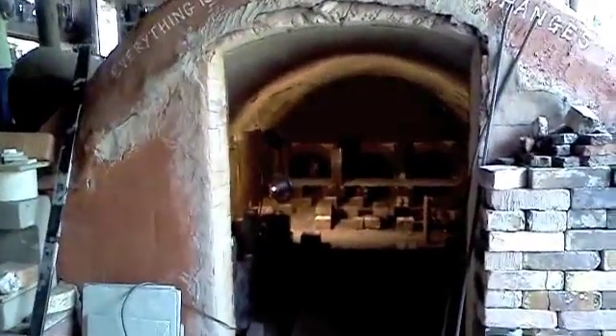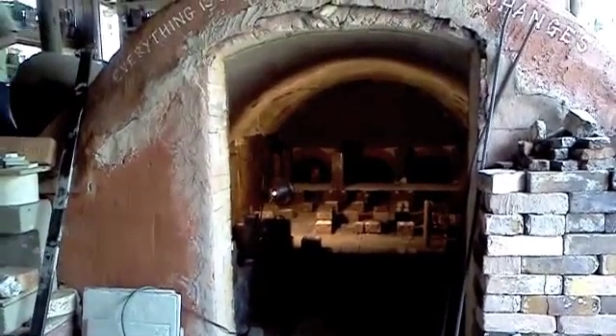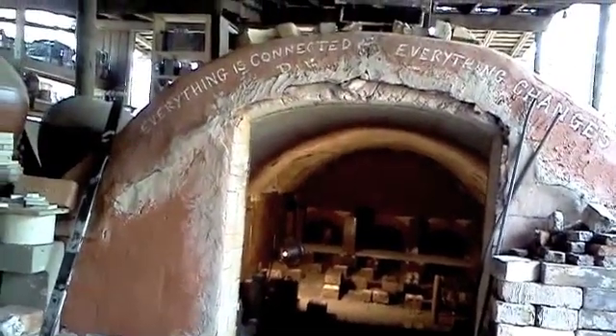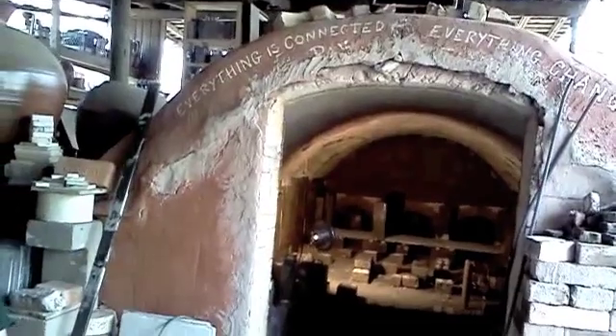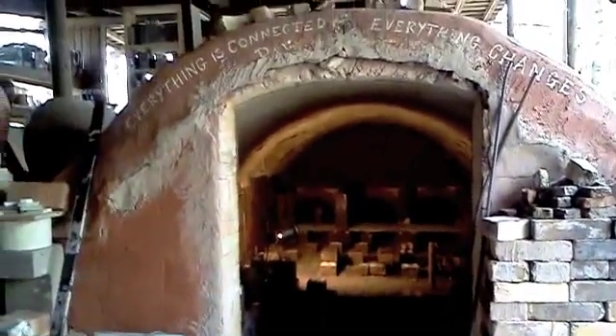And we start preheating on a Monday, and then by Thursday we're pushing the fire underneath the grate. And then by 6 or 7 or 8 that evening we're through the main door. And 24 hours, we usually, the 24 hours were 11 to 13, somewhere like that in the front. And then begin side soaking the second chamber, because the second chamber will go to 10 before you put any wood in it at all.